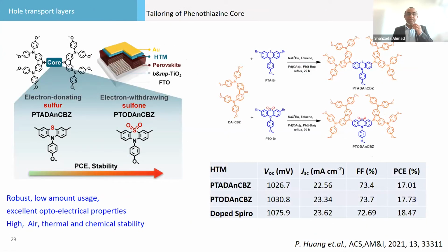Then there's another family. We put the phenothiazine core here. It's electron donating and electron withdrawing. In both groups we have put sulfur and sulfonyl, and this core we have been working on since last year. It's also very easy to synthesize. The yield was also very high here, close to 80%, and similar efficiency: the spiro gives 19%, and this phenothiazine with carbazole gives you close to 18 or 17.7%. But these are more stable.